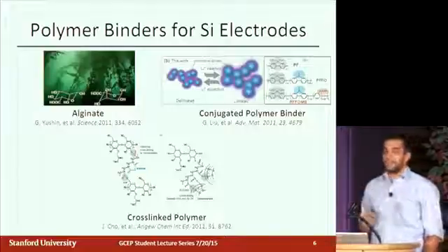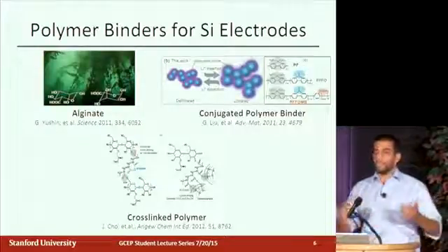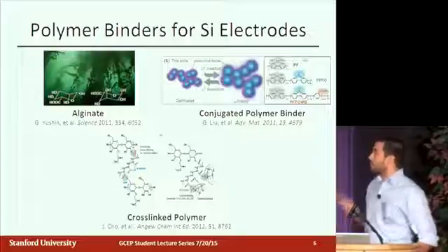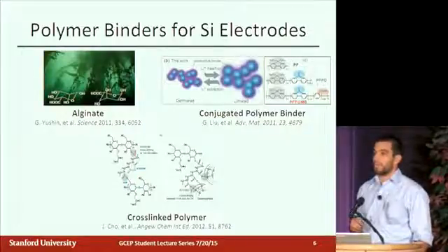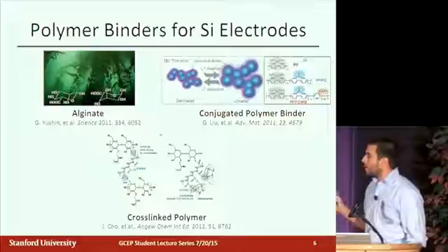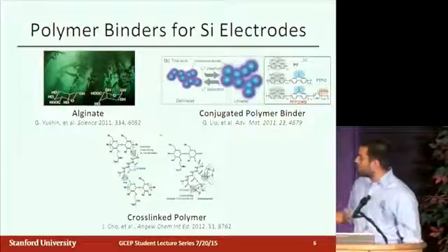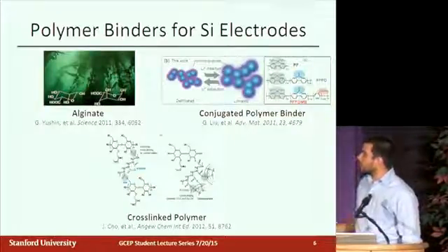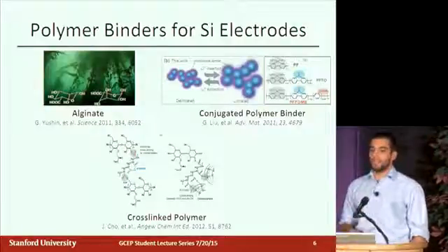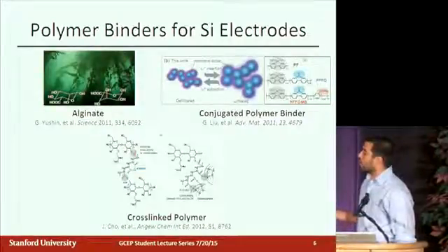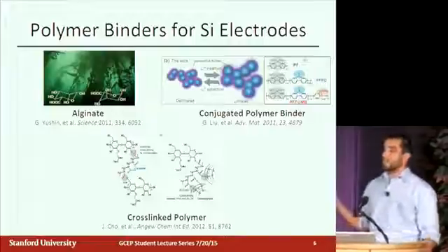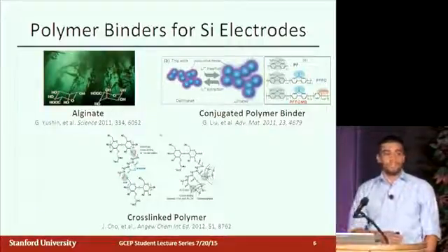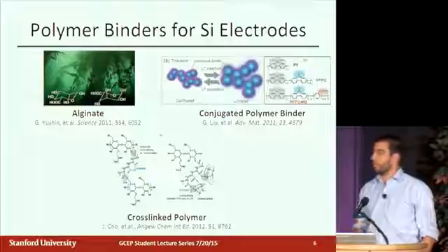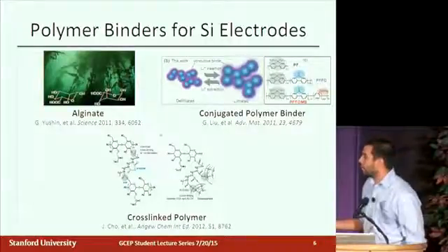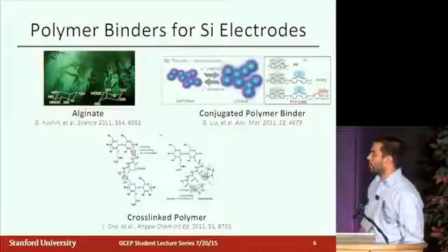They're usually quite cheap, and they're easy to switch in and out of the materials, and they have quite a significant influence on the properties of your battery. And so there are really 3 here. There are carbohydrate polymers that people have been using. They're water soluble, quite nice to work with, very cheap as well. Also, conductive polymer binders. What you can do there is you just replace the conductive additive in your material, and so you're actually reducing the weight a little bit as well. And then finally, people also play with the chemical and mechanical properties of these binders by cross-linking them.